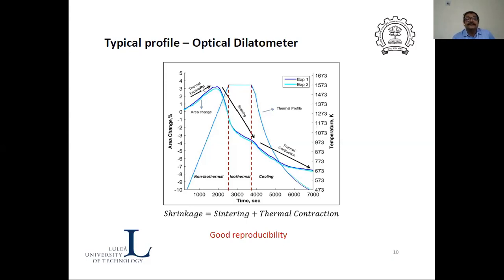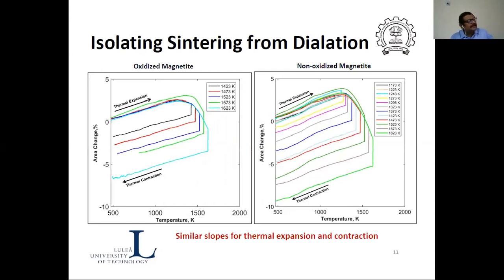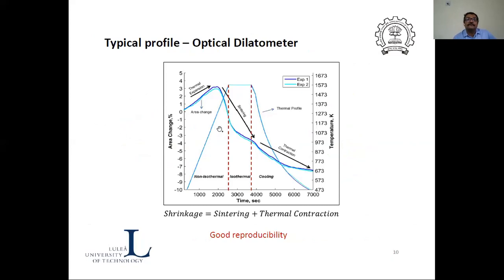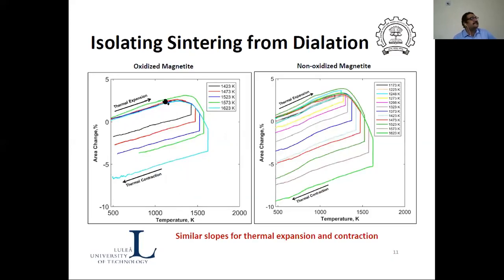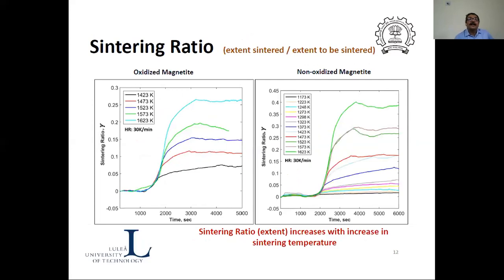Okay. So basically, it is a typical curve which we get from the optical dilatometer. Of course, there are two phenomena happening. One is the expansion, the other is sintering. Actually, one can very easily eliminate the expansion, because if you plot with temperature, you will see that expansion is more or less linear with respect to temperature. So instead of time, I just plot with the temperature. You can see that this is expansion and this is a contraction again during cooling. So I can very easily eliminate that, and I can actually get the change in the pellet size only due to sintering. And that is what we used.